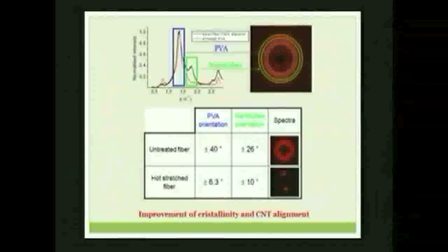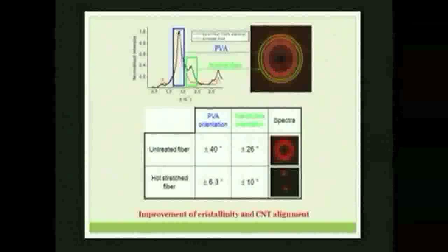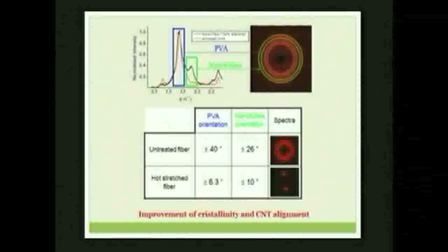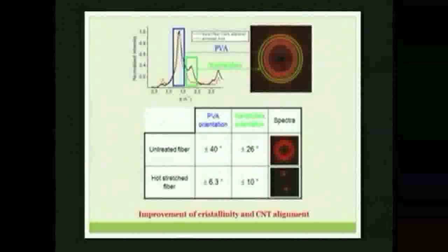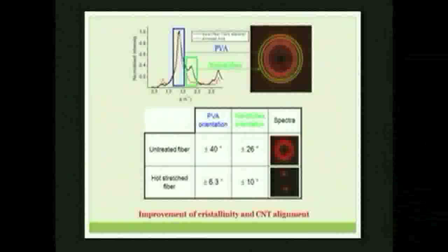Don't read anything, but just to tell you, when we measure the orientation of the nanotubes inside the fiber before this treatment and after this treatment, what we see is a strong improvement of the nanotube orientation. This is the value of orientation of a raw fiber. It's oriented at plus or minus 26 degrees compared to the axis of the fiber. So there is a large distribution, and once you have hot stretched the fiber, you improve this orientation a lot. So the carbon nanotubes are much better aligned. It's also the same for the PVA chains, the polymer chains around, okay?